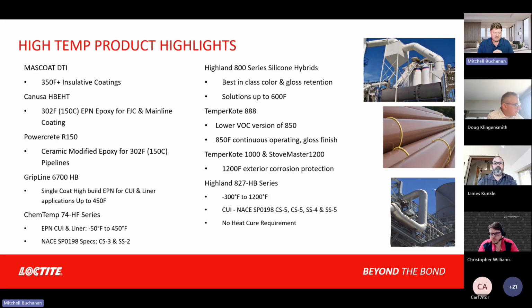Really, you can get to 375 comfortably, but once you get above that, you start running the risk of the heat getting reflected back in and creating a scenario where now you're at 425 or so. And at that temperature, the acrylic binder will start to harden and delaminate. So that's the temperature limit of that acrylic binder. But it is a high temperature for an acrylic, right? Your standard house paint acrylic latex is not going to go up to 350 Fahrenheit.